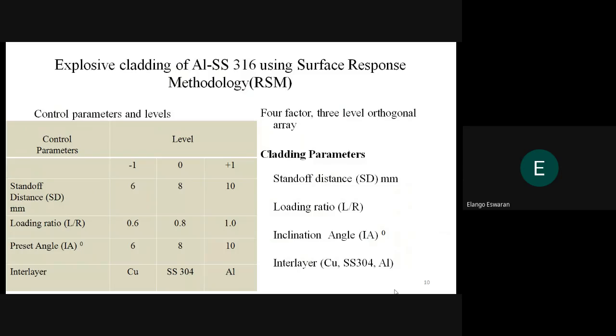To aid the selection of operational parameters, various researchers developed two-dimensional numerical models, design of experiments, mathematical models, and the weldability window. Researchers adopted a response surface methodology, that is RSM, to evaluate the tensile and the shear property of copper low carbon steel explosive clad. Similarly, Tricarico et al. evaluated the length of the intermetallic layer, microhardness, and shear properties by regression equation, while cladding aluminum and steel. In a different way, Tamilselvan et al. employed a full factorial design of experiment to measure the different dimensions of interfacial undulation in titanium and steel 304 cladding. But studies on developing a mathematical model to predict the tensile strength of aluminum 5052 and SS316 explosive cladding with different interlayers using RSM are scarce, hence it is attempted herein.